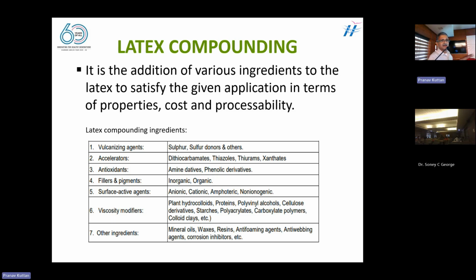So when you use sulfur alone, this is going to happen over several days. When you mix sulfur and keep it in the vessel, it will take days to get the crosslinks. When you heat it, it will still take hours for the crosslinks to happen. So this is not commercially viable. To make it commercially viable, you want to speed it up. You have to cross-link it in minimum time, but obtaining maximum properties. For this purpose, we use some other chemicals which can accelerate this process. These chemicals are called accelerators. These are chemicals which have several functional groups, which are either sulfur donors or activators, which initiate the reaction of sulfur with the carbon.